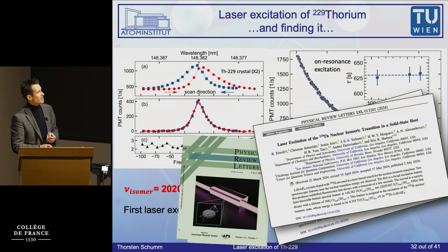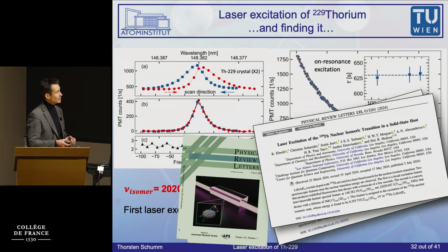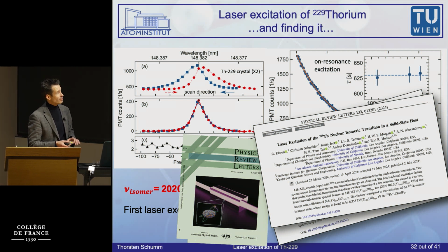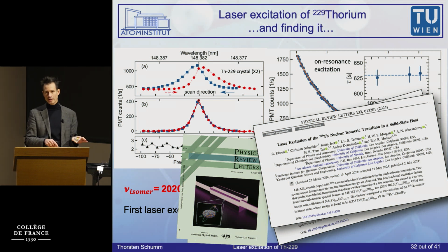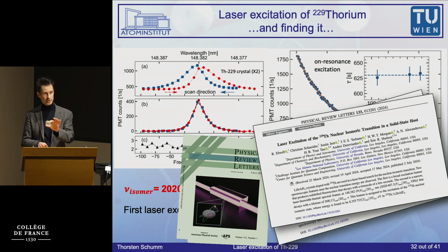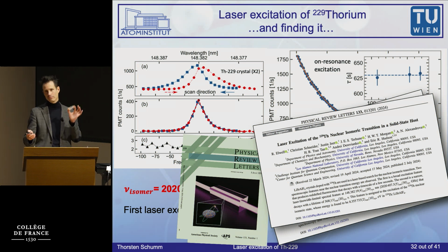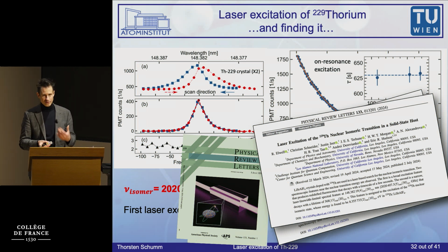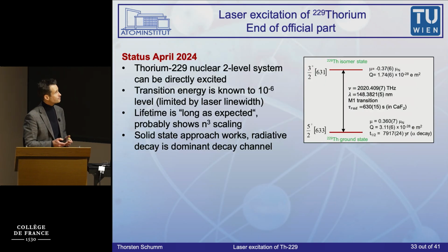Luckily, 3 months later, a US group at UCLA repeated that experiment. They dialed in our number, but they had a different host material. They had a more complicated crystal, lithium, aluminum, strontium fluoride, and they found exactly the same wavelength to a gigahertz precision. So that kind of verifies that this is not a material property, but really a nuclear result.